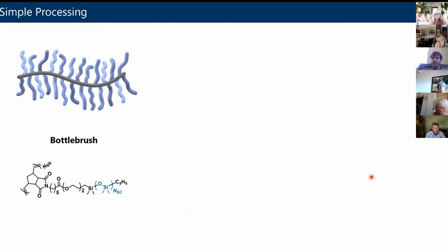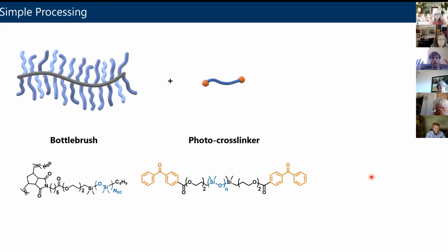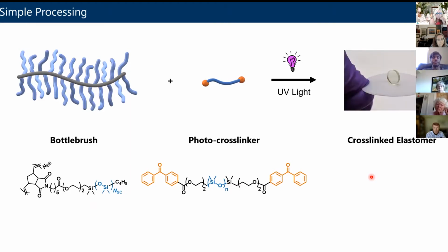The processing, once you've got the Bottlebrush, and once you've got this photo crosslinker, is really easy. You just mix them together at room temperature. They're miscible. You shine a little bit of light to activate the benzophenone, links all the chains together, and it's no longer a viscous liquid. And you can see that in this picture where Veronica has stood the sample that's been cross-linked up on its side to show you it's not flowing.